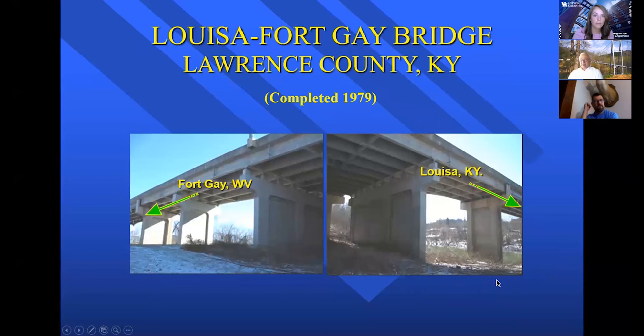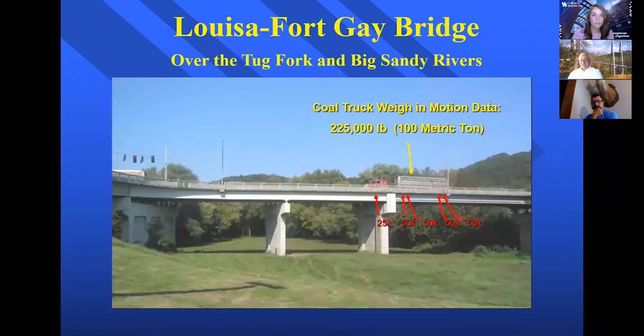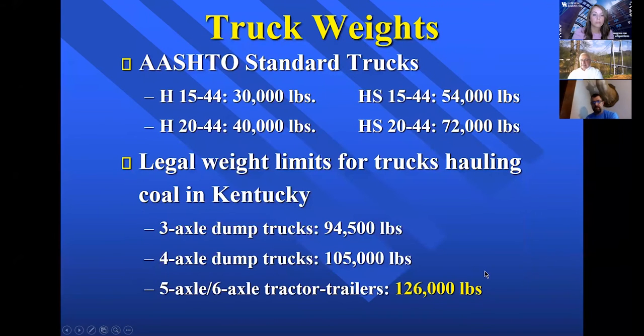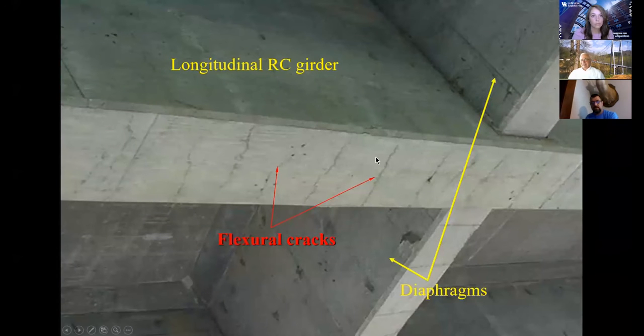So the first bridge we repaired with this was the Louisa Fort Gay Bridge. And this bridge sees quite a bit of haul trucks, and some of them, using weigh in motion, weigh over 200,000 pounds. And the legal limit is 126,000 pounds. So the bridge is carrying close to double what it's designed for. So of course, we're going to start seeing cracks and so on in the beams. These cracks are really not that serious. Usually we don't do the repair with carbon fiber for these cracks.